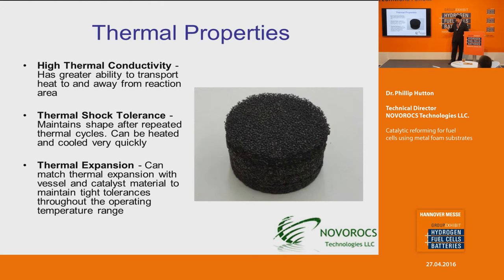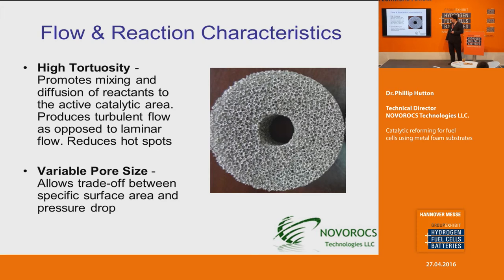And thermal expansion. We can get metallic foams in stainless steel, copper, aluminum, ferroalloy, which is a very high temperature metal, nickel, or even a combination thereof. So we can get nickel coated on metal. So we can actually match the thermal expansion of the foam with the reactor vessel. As the reactor vessel heats up, it'll expand, and if you want to maintain good contact, you can match that thermal expansion with your metallic foam, and we can match it with the catalyst material. So if you have problems with your catalyst material flaking off, we can try to match the thermal expansion and see if we can maintain that catalyst material on that substrate.